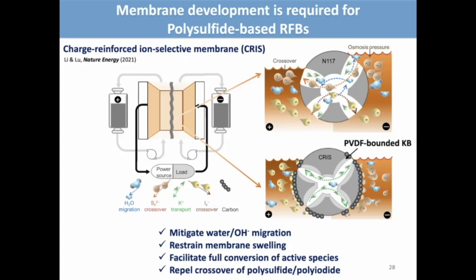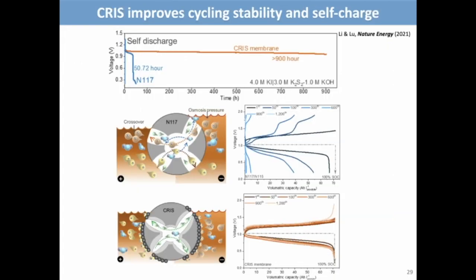We developed a PVDF-bonded Ketjen black coating and put it on both sides of the membrane. This membrane has a hydrophobic component, the PVDF, which can penetrate into the pores, and this can mitigate water and OH migration. And this carbon phase can absorb the polysulfide on the negative side and the polyiodide on the positive side, which can then further repel identical ions from crossing over to the other side. So using this strategy, we hope to alleviate the crossover issue in the polysulfide redox flow battery.